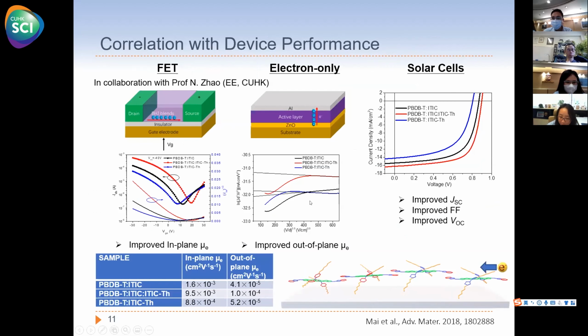Okay, so finally we can correlate this structural order with the device performance. In collaboration with Professor Zhao Ni in the EE department at our school, we are able to measure the in-plane electron mobility and out-of-plane electron mobility, and we also fabricate solar cells. We find the in-plane electron mobility is almost an order of magnitude higher for the ternary cell than the binary cell. Okay, so that means this backbone order indeed forms a long-range electron transport pathway to facilitate electron transport and